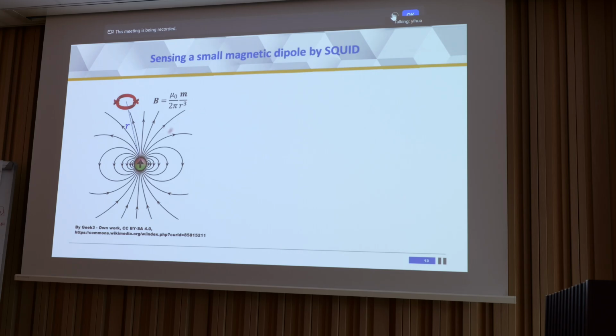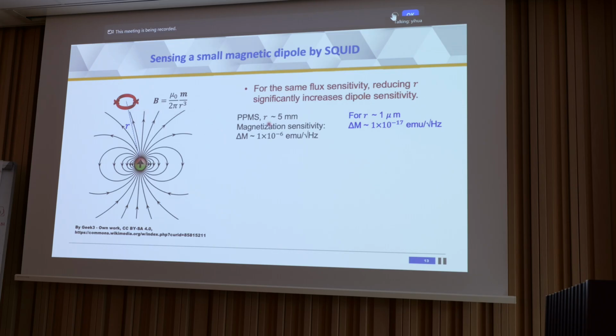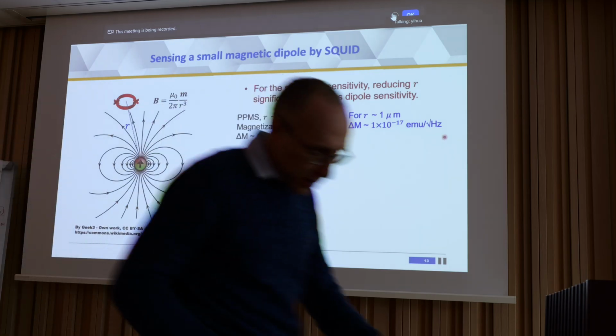For example, if you have a magnetic dipole, its magnetic field decreases as 1 over r cubed. If you put the SQUID away, say around a millimeter scale away, the magnetization sensitivity is on the order of 10 to the minus 6 emu per root hertz, which has been very powerful and has been widely used for material characterization in bulk systems. However, if you can move your SQUID probe very close to a sample, say around 1 micron, then the magnetization sensitivity increases to 10 to the minus 17 emu per root hertz.